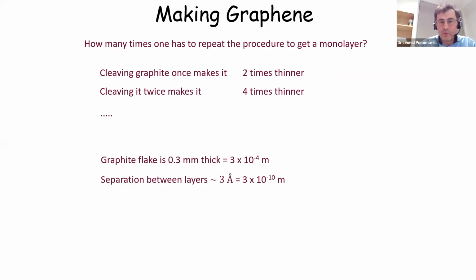Assuming that our initial flake was roughly 0.3 millimeters thick, which is the normal thickness of graphite flakes that are available and which researchers actually use for making graphene, 0.3 millimeters means 3 × 10⁻⁴ meters. It's hard to say what the thickness of a monolayer is, but as a good approximation, we can use the distance between layers of graphite, which is well known from X-ray diffraction. This separation between layers is approximately 3 angstrom, or in SI units, 3 × 10⁻¹⁰ meters. So we have to make our graphite crystal 1 million times thinner using Scotch tape.